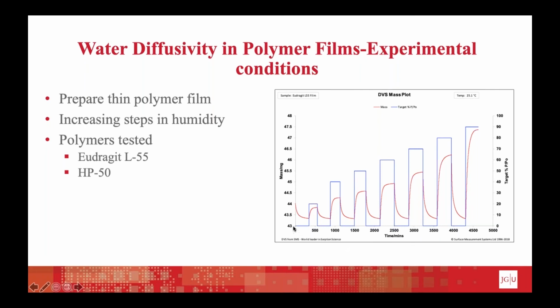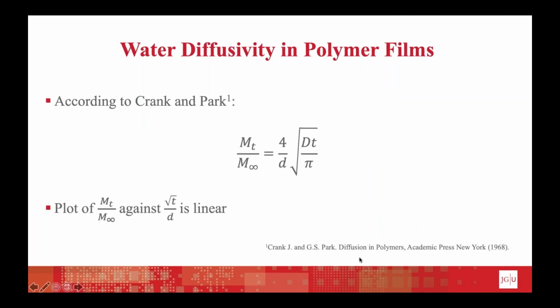So we dried the polymer film first to get the zero mass, and then increased the relative humidity to, for example, 20% or even up to 90%. And from this, we could calculate the water diffusivity. And this can be done in the following way.